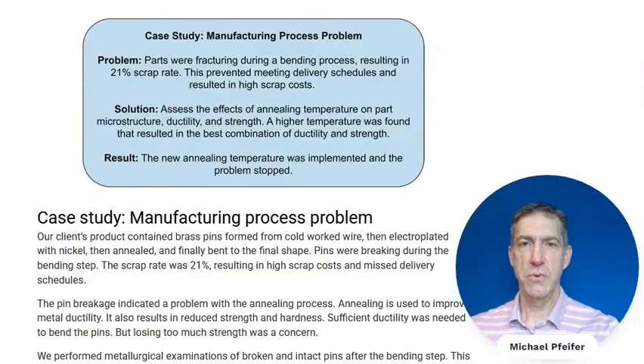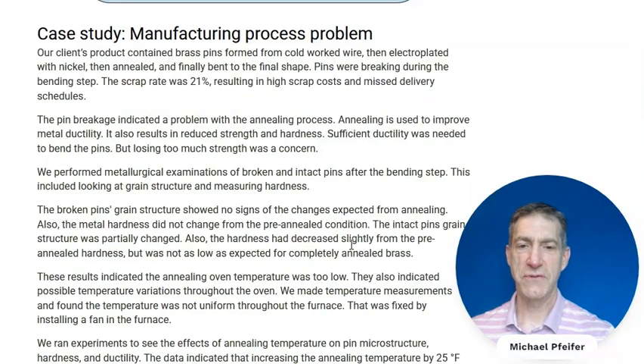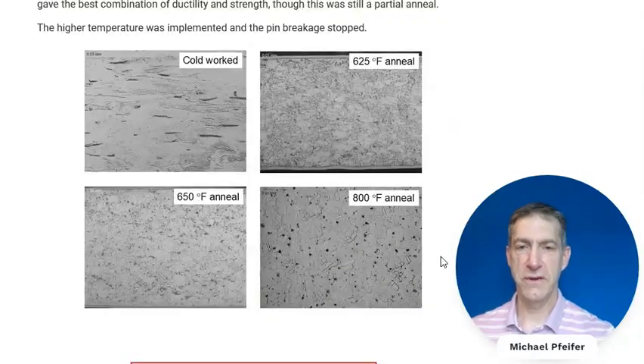So we then ran experiments to evaluate increasing the temperature on the annealing, and we saw that increasing the temperature by 25 degrees resulted in a partial anneal with an increase in the metal's ductility and a slight decrease in the hardness. And the hardness just indicated that the strength had not decreased all the way as it would with a full anneal. So what was implemented was an increase in the temperature by 25 degrees Fahrenheit, which resulted in the hardness and ductility needed to be able to bend the pins while the pins still had the strength needed for the application. So the micrographs for the metal in the different conditions are shown here.